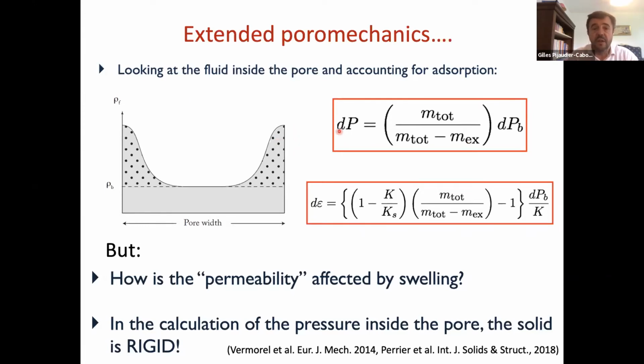You compute the real pressure applied inside the nanopores as a function of adsorption, using a standard poromechanical model, and hence in this case with the effect of adsorption, the swelling. That provides results which make sense, but I have not seen, to my knowledge, results on how the permeability would be affected by swelling.